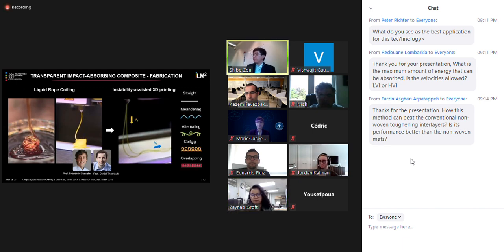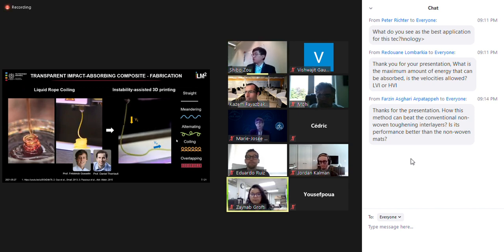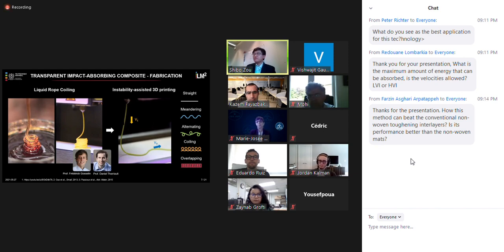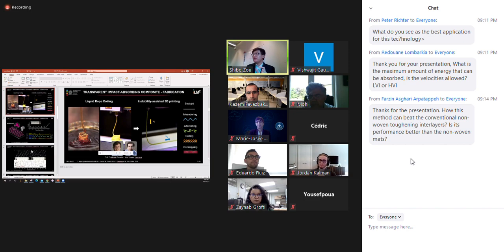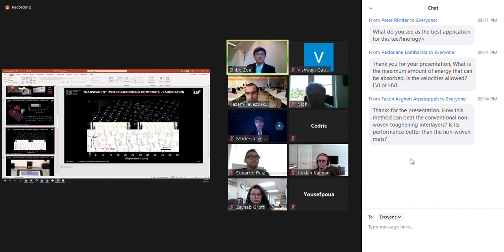Yes. So basically, in our composite project, we chose to use alternating fiber. It's just because the distance between each loop in this alternating fiber is larger than the coiling fiber. That makes it easier for us to make this 2-layer fabric. If we use the coiling fibers, the distance between each loop is much closer, and we have no problem printing the first layer. But when we print the second layer, the first layer has created a non-flat surface, so the deposition of the second layer coiling fiber will be much disturbed. We wouldn't have this regular coiling fiber, or we wouldn't even have the sacrificial bonds. That will lead to a difference in the mechanical properties between these 2 layers.